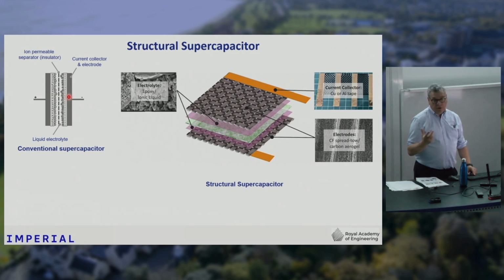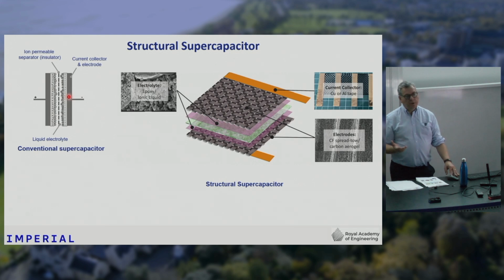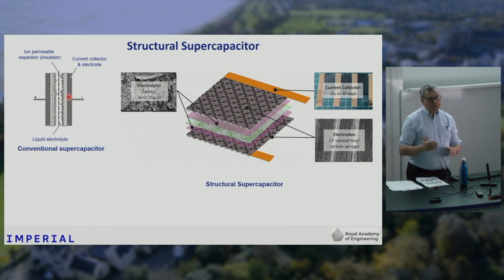We have an electrolyte, and rather than being a liquid electrolyte, it's actually a blend of a structural material and an ion transport material. What we use is something called an ionic liquid. The best way to think about it is that it's an ionic material that's a liquid at room temperature. If you took table salt up to 800 degrees C, it would become a liquid, and you could use that as an electrolyte because you've got sodium and chlorine ions. If you apply a voltage to that, it will force those ions to move, and you can store charge. Ionic liquids are ionic materials which are liquid at room temperature, so you can use them as an electrolyte. And what we use are two organic ions, an anion and a cation.